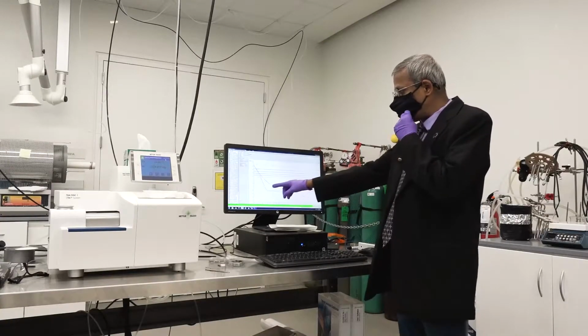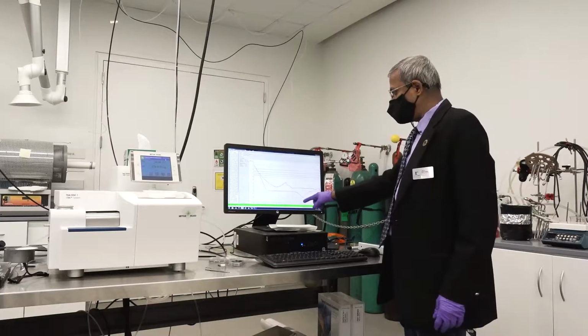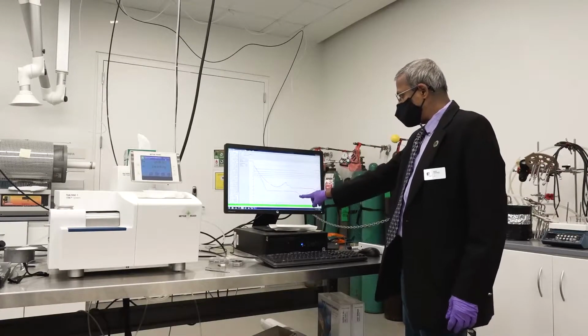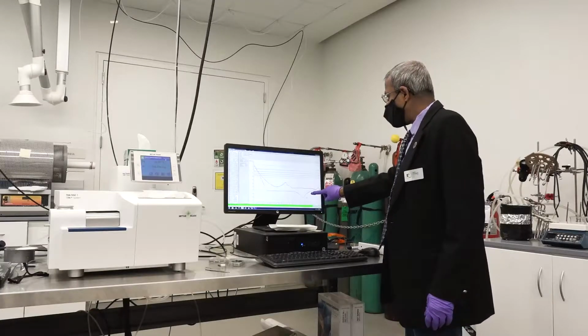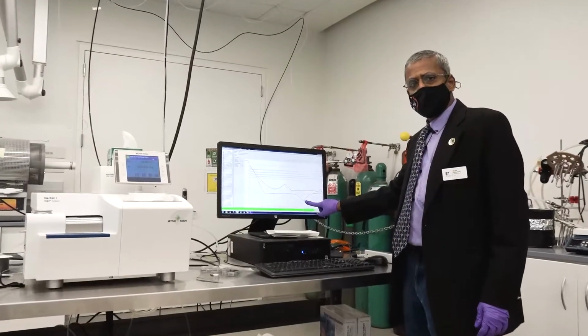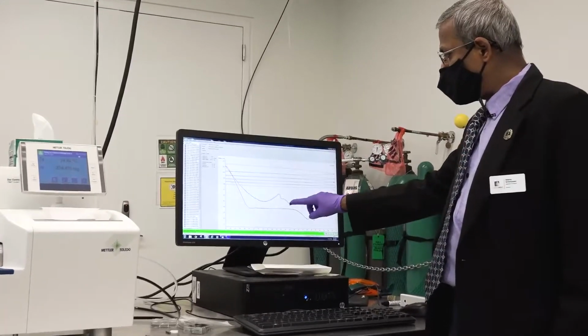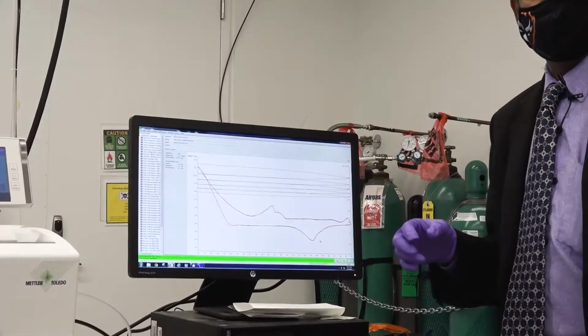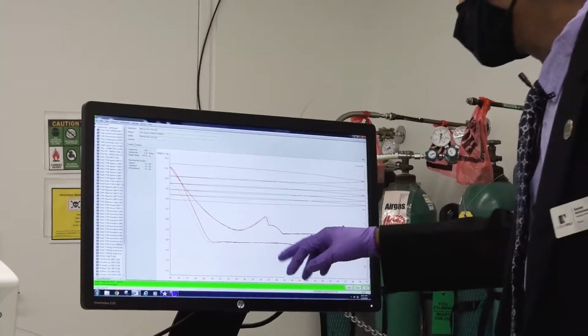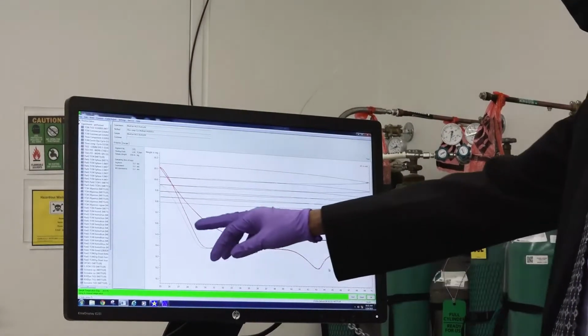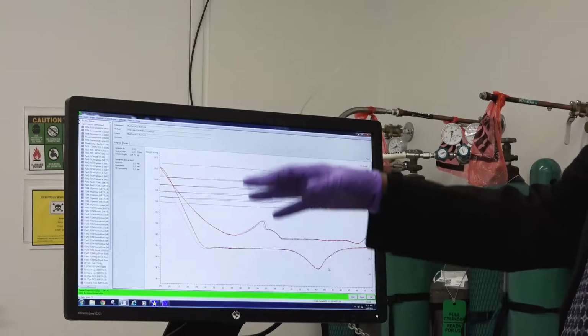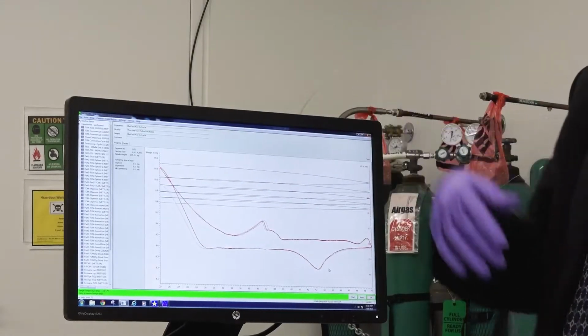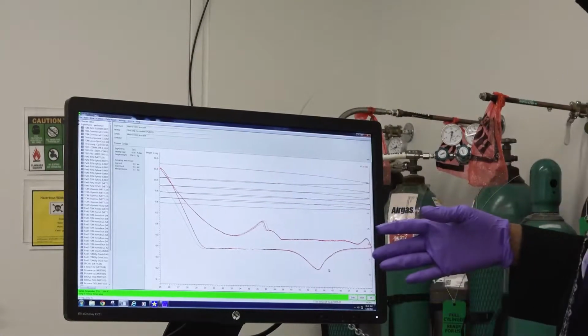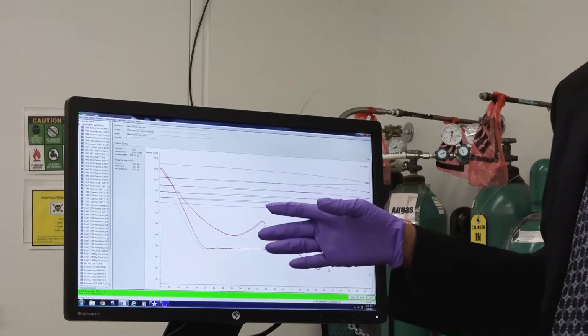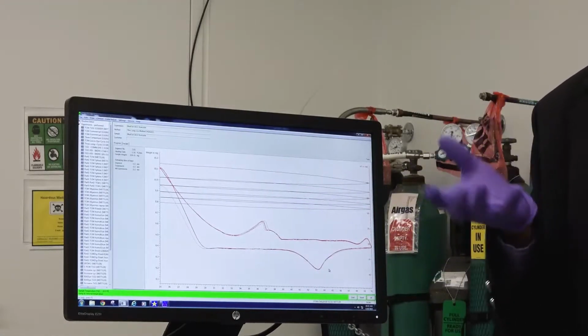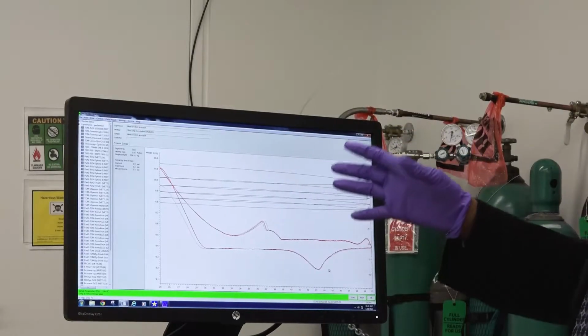What you see here is an encapsulated polymer sample. When you heat the sample, it goes through a transition around 43 degrees, and then when you cool the sample, it crystallizes back around 34 to 35 degrees. So we have done a couple of cycles to show that the heating and cooling cycle is going on reversibly, the color change property, and moreover it's not affected by melting. Because of the encapsulated material, the sample does not get melted.